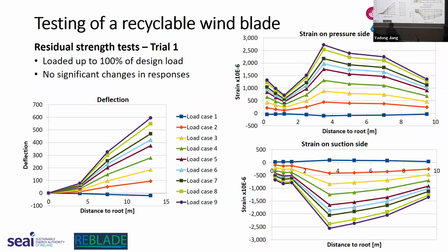And after that, we analyzed the deflection and strain data. Compared to the previous static test, we carried out more load steps. So there is an increase in the strain, but the same as the previous test, the maximum strain occurred at 3.5 meters from the root. And if we compare the deflection and strain readings with the static test before the fatigue test, there is no significant change of the strain and deflection. So that means there is almost no damage during the fatigue test, which is a very good thing.